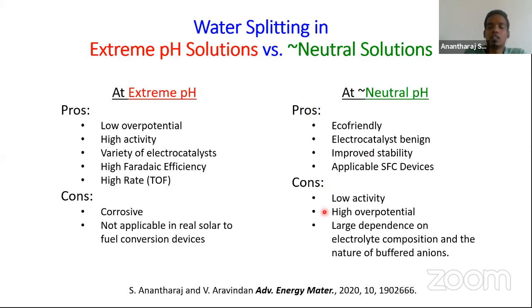And the cons are because of very low mobility of water molecule, because we always have to depend on the supporting electrolyte and the buffered anions in the solution, neutral pH solution. It delivers low activity and it always requires high overpotential, which means that we are losing energy here. And the activity depends largely on the electrolyte composition. And sometimes if it is a more homogeneous catalyst, it also depends on the nature of the ligand that we use for making the catalyst. So I'll be talking about all this in detail in upcoming slides. So let's see